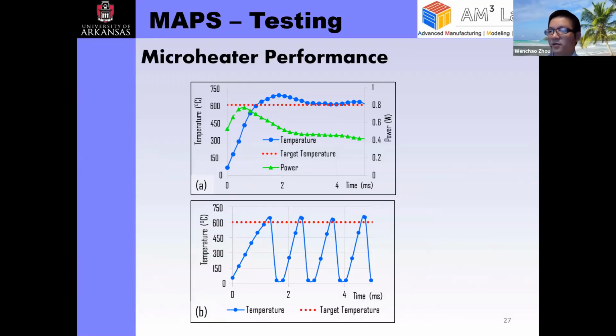So we also did a cycling test, and as you can see here, the micro heater can be heated up to over 600 C and immediately cool down to room temperature and cycle over in millisecond time scale, just because the thermal mass of the micro heater is so small. As soon as you turn it off, it will cool down immediately. It doesn't need any additional cooling mechanism.